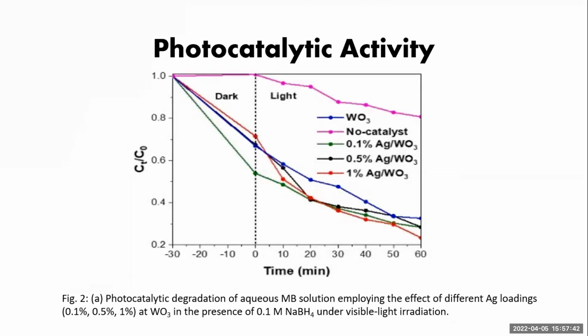So photocatalytic degradation of aqueous methylene blue solution, employing the effect of different Ag loadings. Here we can see some graphs. One is simple WO3, second is without catalyst, and next is 0.1% Ag in the WO3, then 0.5% Ag in the WO3, and then 1% Ag in the WO3. In the presence of 0.1 molar NaBH4 under visible light radiation, we found these graphs. Here is the photocatalytic degradation reaction rate using 0.1% AgWO3.